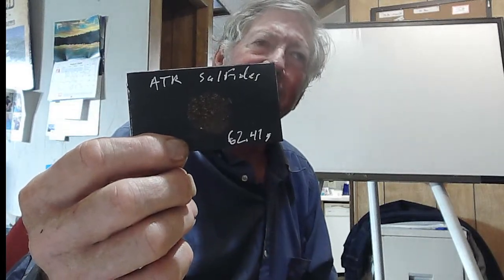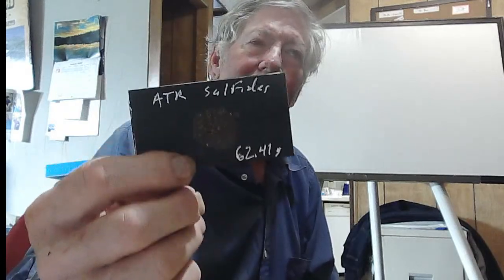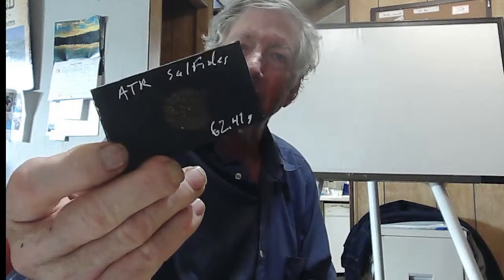Okay, I take one of my little black cardstock cards and write down what the sample is. In this case, it's across the road sulfides. This is that silver stuff from that one sample that was so much of it. Then I put the number of grams of the sample I had. This is what I panned this morning. We sent off some for assay, and then I just panned the rest down and got 62.41 grams. Then I take a little drop of white glue, stick it on the card, and put some of the sample on there. Now I have a permanent record of this particular sample, not only how much it weighed, but what it actually looks like.